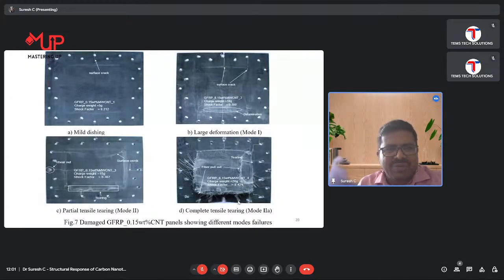And again for 0.15, the amount of crack has reduced compared to 0.1 for 5 gram. And here also all the edge delaminations and cracks got reduced compared to the 0.1 weight percentage. Here also the structure withstands much higher load and the damage is much reduced compared to the 0.1 weight percentage of the carbon nanotubes. Here, if you see, the damage at 20 gram is slightly reduced, but still we are not able to safeguard the structure from the damages.